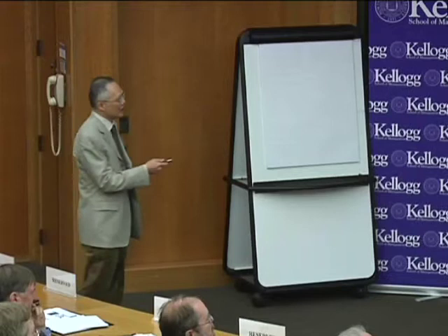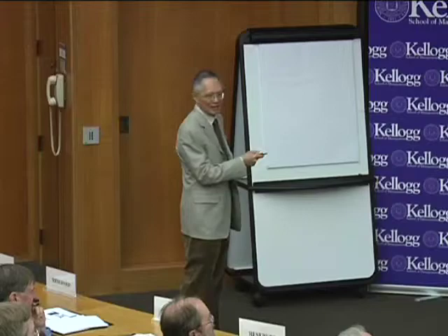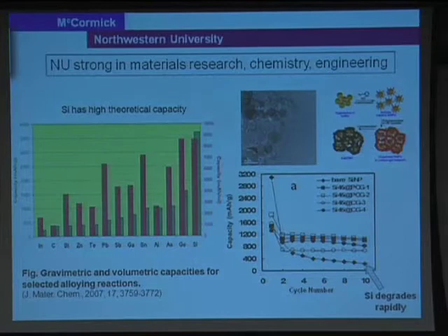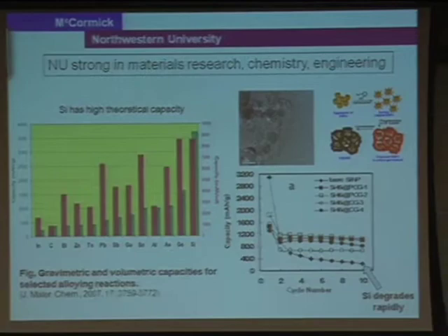By understanding why that occurs, we thought that what we can do is take this silicon material, these little black dots, and protect them by encapsulating them with a carbon material. This carbon material is electrically conducting, and we form a very thin layer of it, since this little dot of silicon is only about 20 nanometers in size. And indeed, by forming this protective carbon, you stabilize the material much better than without it, but still it's not good enough.